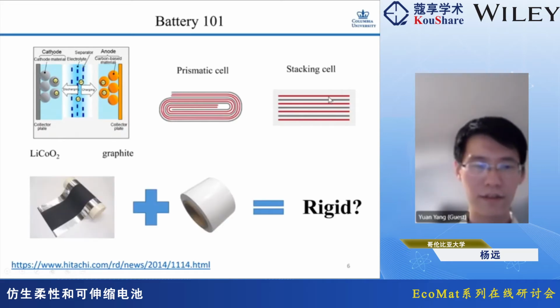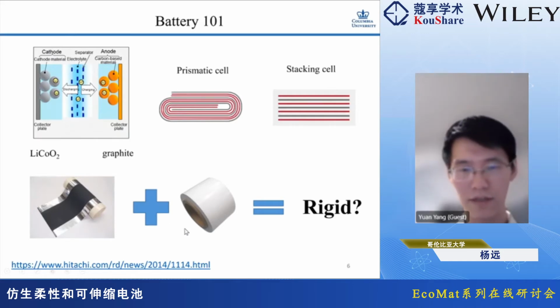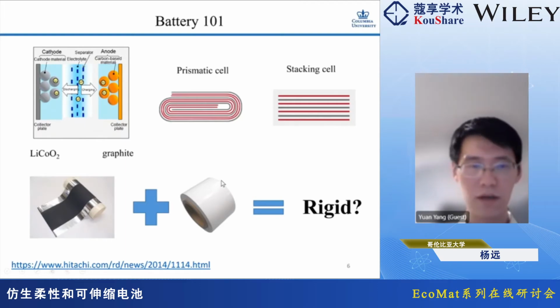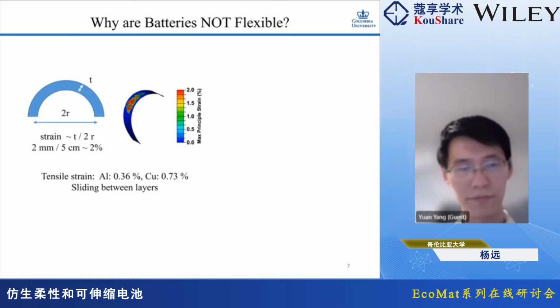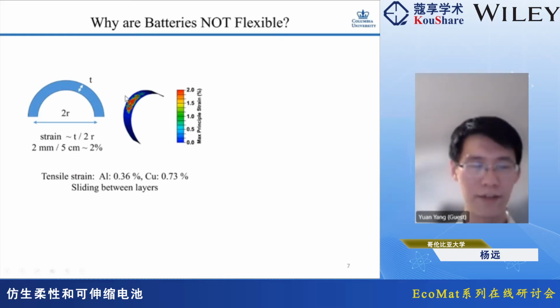If we look at the individual components, they're actually highly flexible. You can see from here, this is the lithium cobalt oxide positive electrode on aluminum foil, and the separator is just a very thin polymer. So why is the battery rigid instead of flexible? The reason is actually the thickness. We want to make the battery thick so it can store more energy inside. But when you bend the battery,